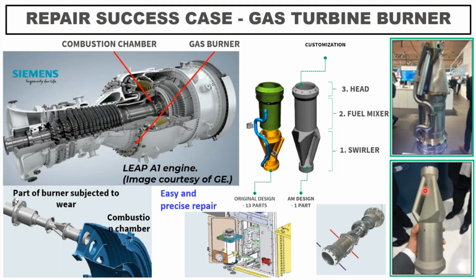The conventional approach used to be weld overlay, but there you're constrained by the composition or availability of filler rods, which have a different composition. Now with laser additive manufacturing, you can use the same composition to refurbish. And it's not just refurbishing - you can actually create a completely new component.